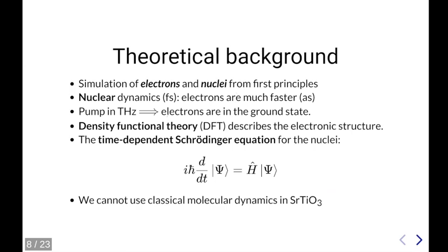And since in this case we are pumping with terahertz radiation, and strontium titanate has a band gap which is of the order of 3.2 electron volts, so it's higher than visible light, we are actually not exciting electrons directly with the pump. And so we can separate the nuclear dynamics, which occurs on a femtosecond time scale, and assume that the electrons remain in their ground state, within the Born-Oppenheimer approximation. And instead, we need to solve the full time-dependent Schrödinger equation for the nuclei.